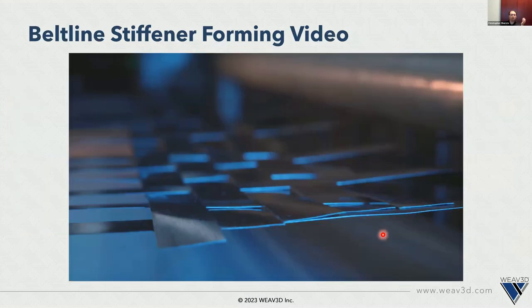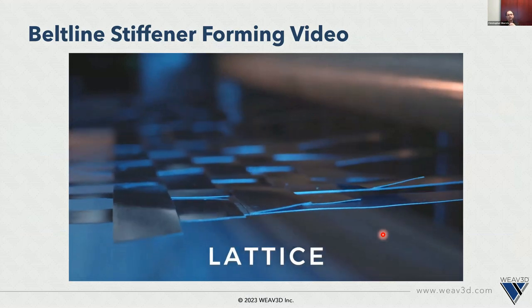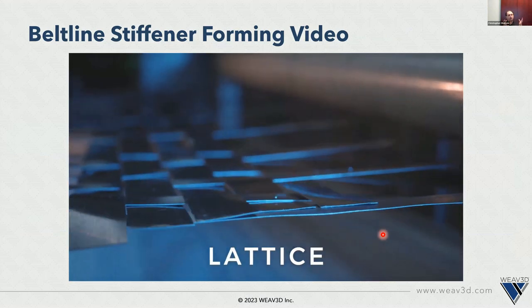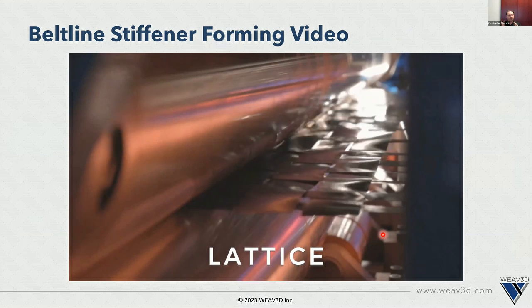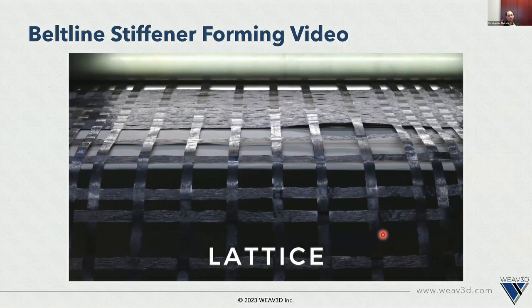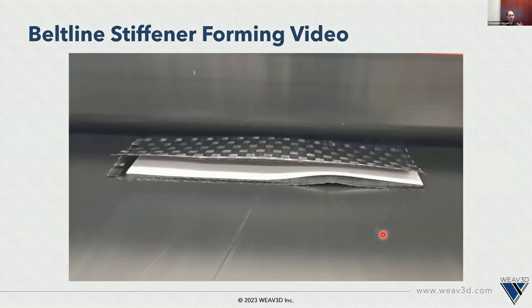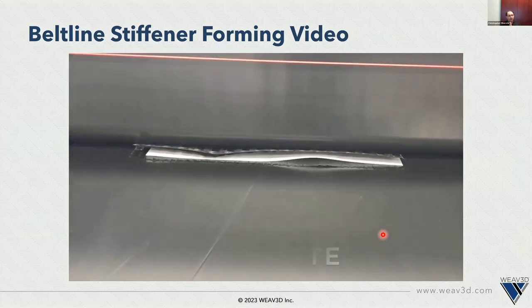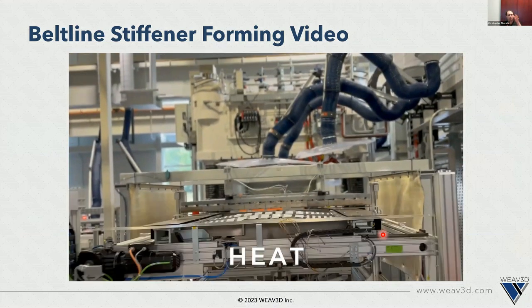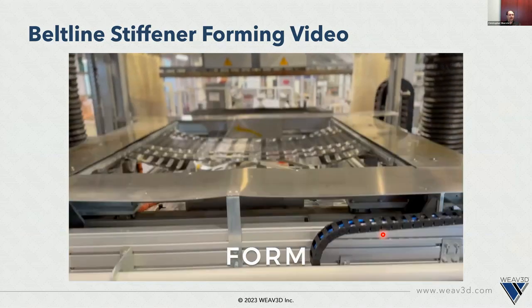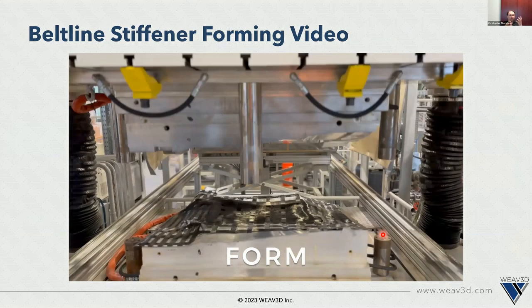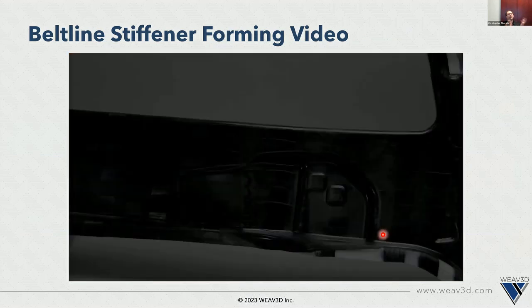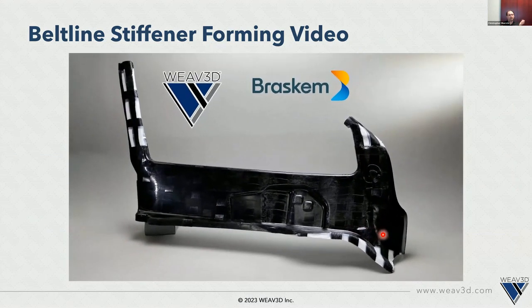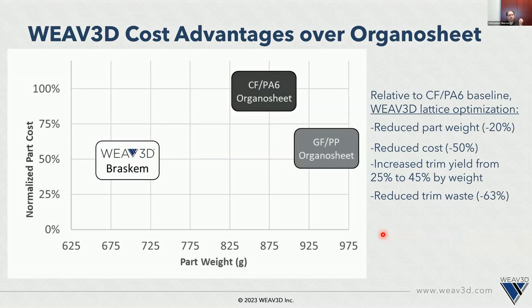So what this looks like from an overview perspective, our manufacturing process: we're producing a lattice material. So it's going through our process as a tape, it comes out fully consolidated. We then did a lamination process, as I mentioned, making sort of that sandwich of lattice, polypropylene, lattice. And then we formed the actual part with a thermocompression process, and then we did a water jet trim to finalize the geometry here.